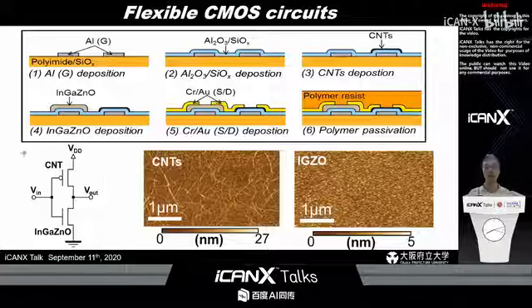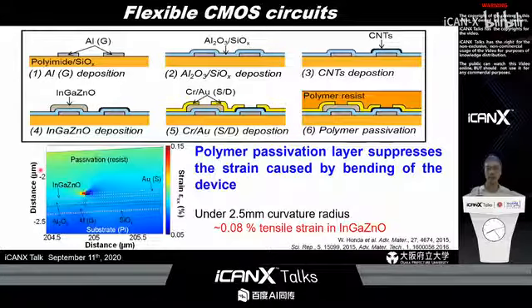So our device structure is like this, the fundamental CMOS structures. The reason why we deposit the polymer as a passivation layer is to suppress the strain caused by the bending of the device, since this device is a flexible transistor circuit. By adding the passivation layer, we can reduce the strain to 0.08% under a 2.5 millimeter curvature radius. Of course, if you control the thickness more, we can reduce the tensile strain even more under such a low bending radius.